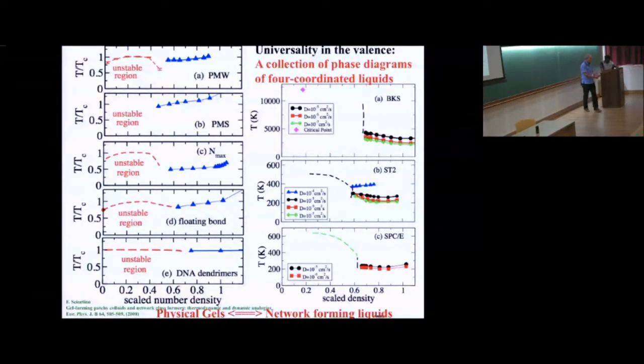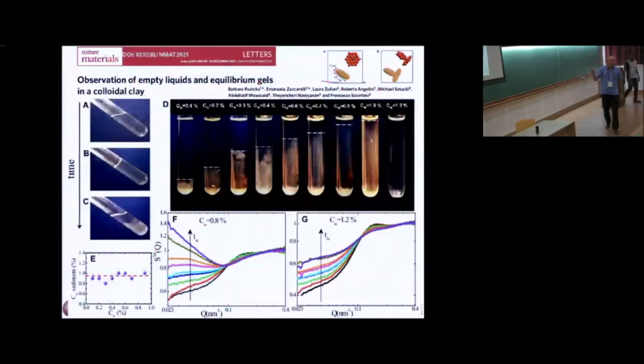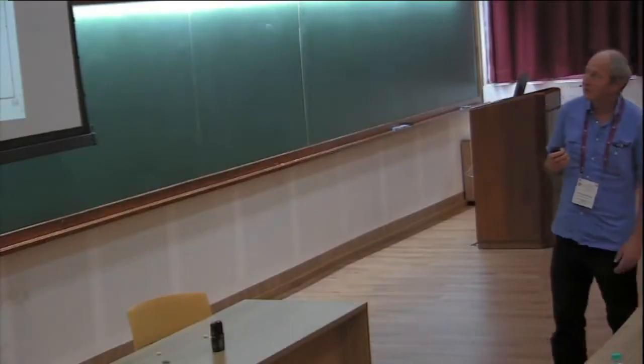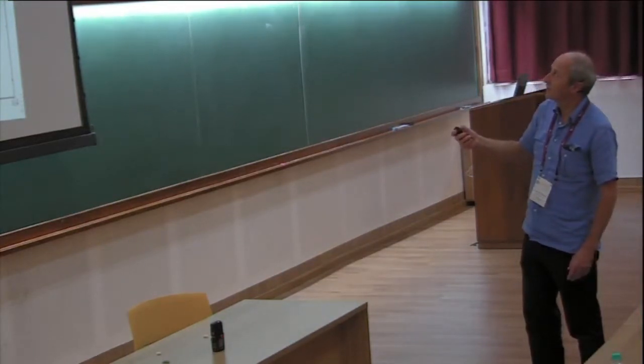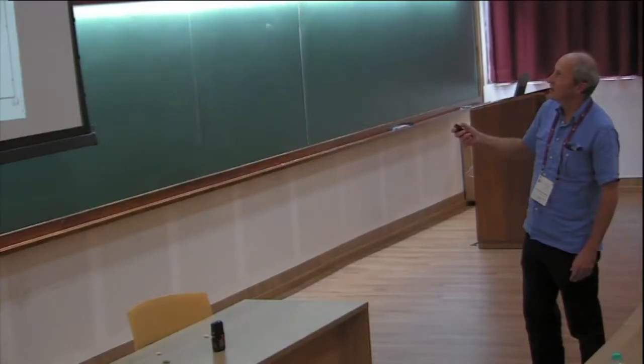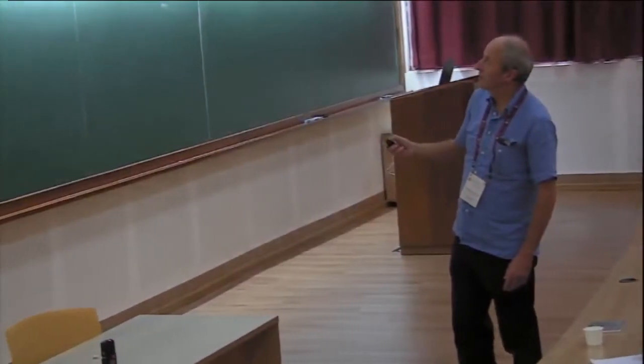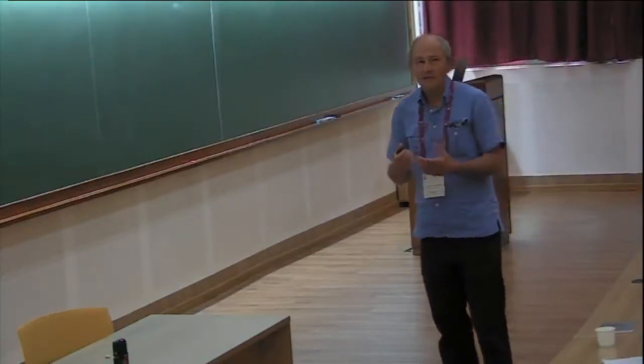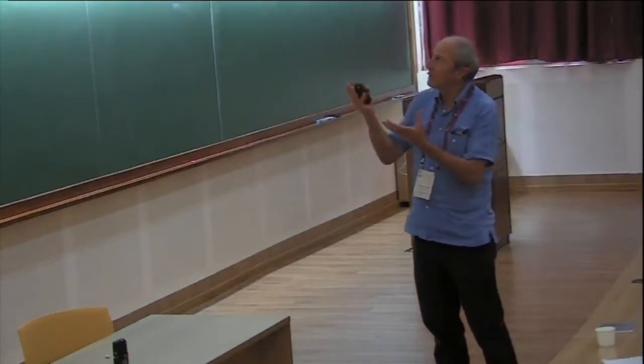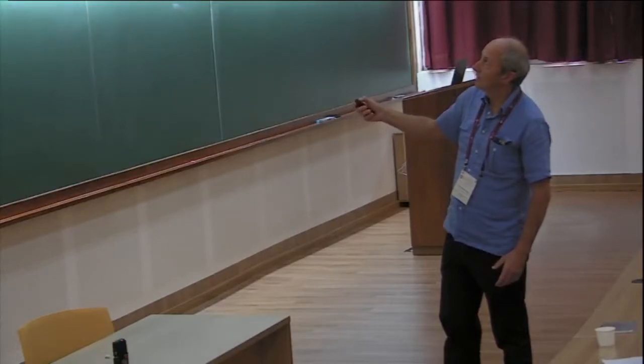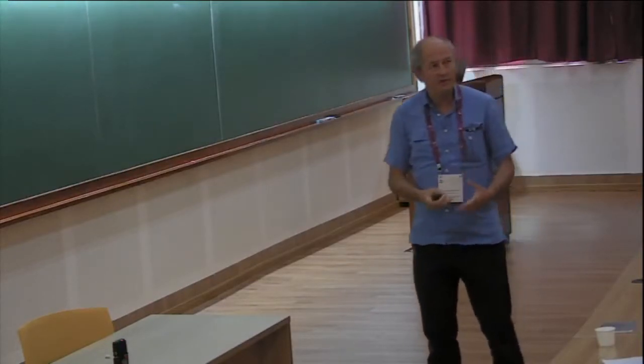I didn't check. Anyway, let's see an experimental check of these ideas. This is a clay, a soft matter system. It's a small platelet particle, which has charges of 2 different types. They are positive on the rim and negative on the surface, so that they prefer to form bonds of this type, T-type bonds. And in some sense, those particles can form a limited valence number of contacts. You can simulate this with a very simple model, and you recover the same physics of limited valence particles.